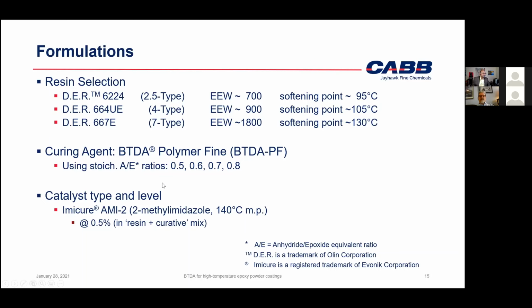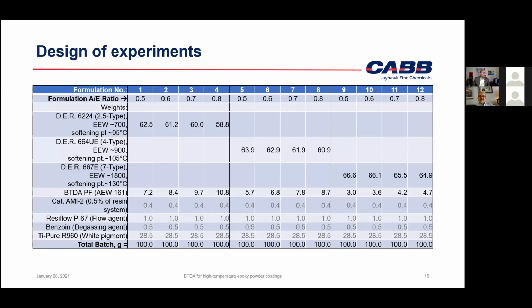And then I think you covered it, but just in case, the A over E ratios, the anhydride to epoxide equivalent ratios that we used, 0.5, 0.6, 0.7, 0.8. And most of the data we'll actually start to see 0.6, 0.7, 0.8, because 0.5 was a little too low for these kinds of systems, which we kind of knew, but we still included that anyway. But 0.6, 0.7, 0.8 were more along the lines of what we needed to do.